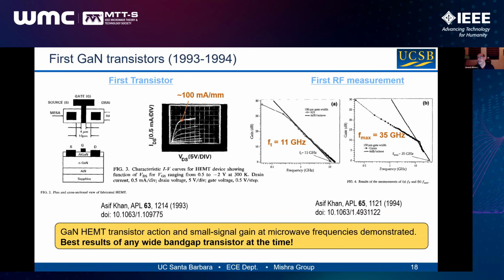The first GaN transistor was also demonstrated. AlGaN/GaN transistor was first demonstrated in 1993 with an fT and fmax of 11 and 35 gigahertz. So in these days, in the early 90s, we saw that there were some real possibilities, but people were still a little skeptical because gallium arsenide had a big substrate, it had a lot of momentum.